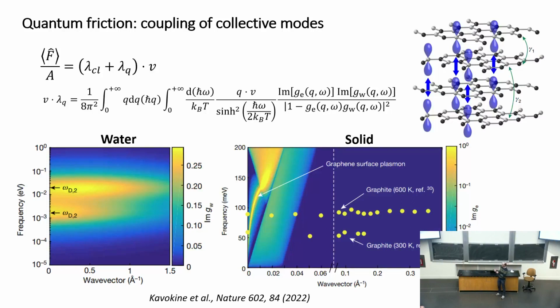The quantum friction term is suggested to come from coupling of collective modes in the water phase and in the wall. Essentially, you look at electronic fluctuations, charge fluctuations in your water near a wall, which has electronic excitations. And the more the energy of your excitations has a similar frequency, the more water can lose momentum when it flows over these surfaces by doing excitations in the electronic system.